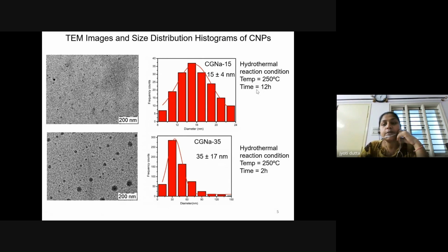However, we observed that the second set of nanoparticles, which have a 35 nanometer size range, were obtained when the temperature was 250 degrees centigrade and the time for the reaction was 2 hours.